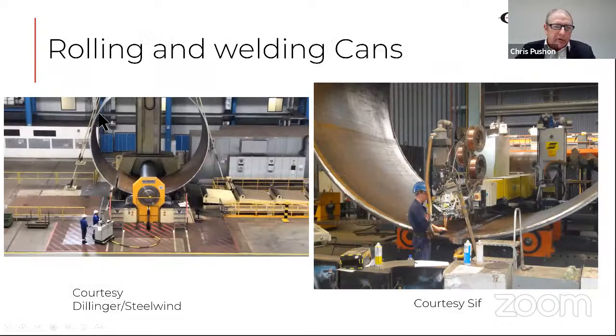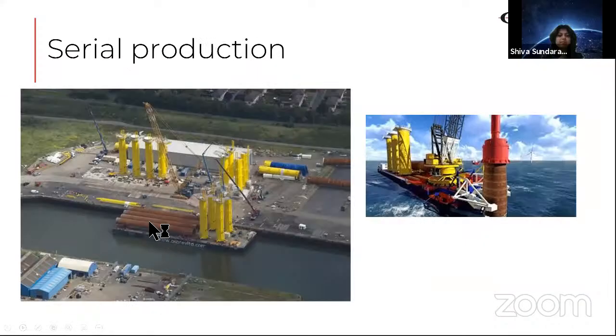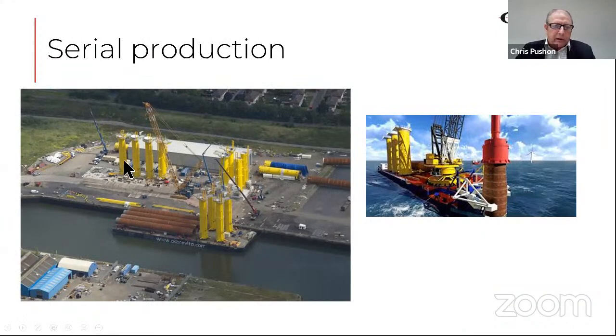Again, the way they're produced is that you roll a can, and this looks quite thin, but this is actually 80 to 100 millimeters thick. It can be up to 125. And then you carry out, in this case, long seam welding with multi-wire submerged arc welding. And these are the productivity issues that you have to be able to do this quickly enough to get the production rate you need. And this is a typical lay down for an offshore wind farm.